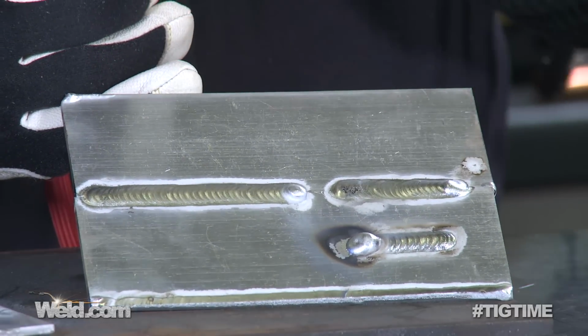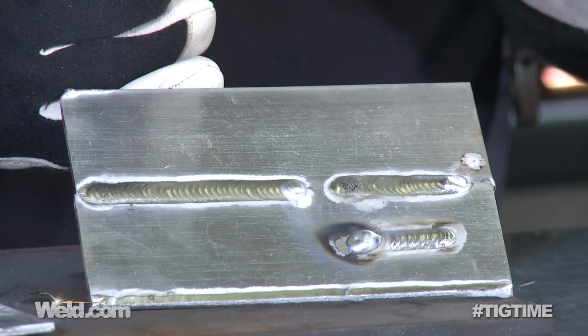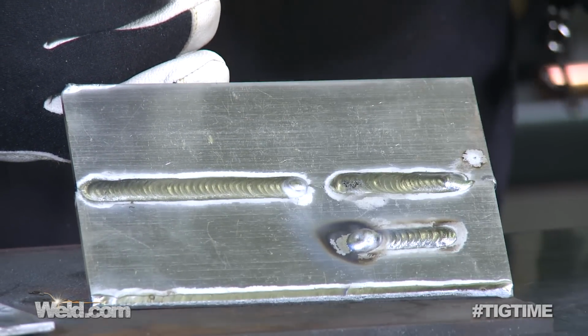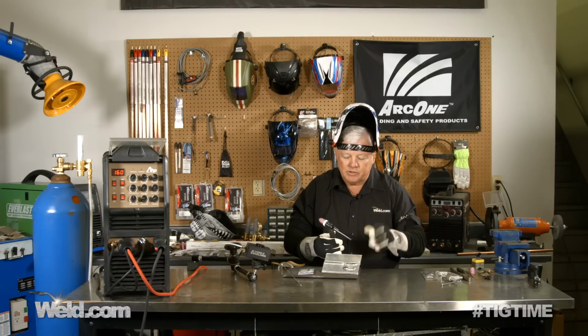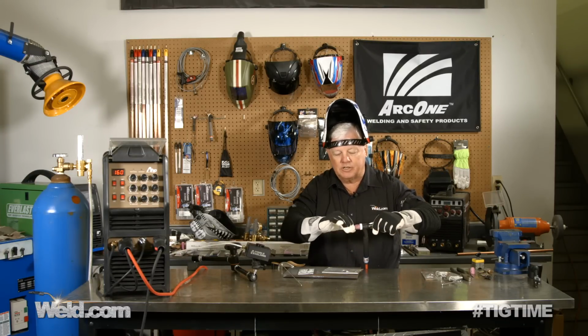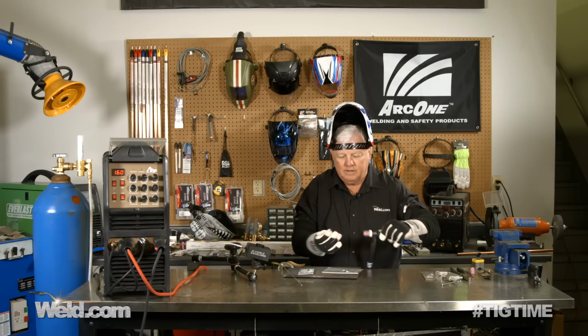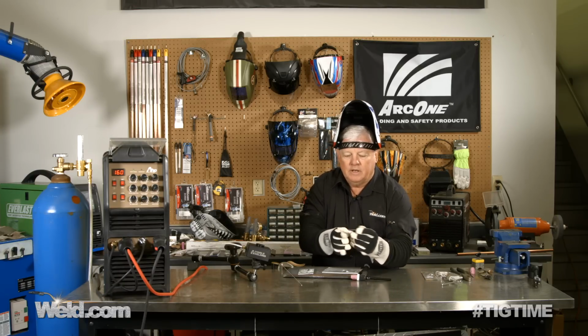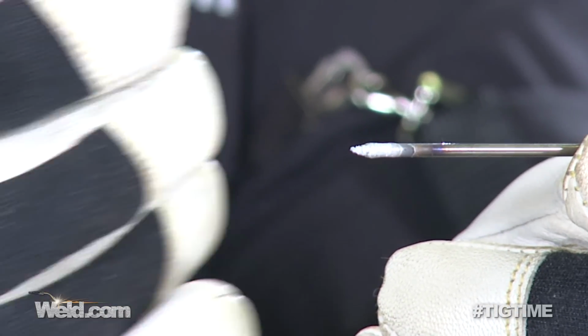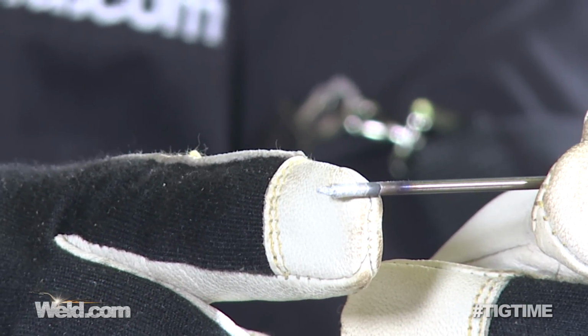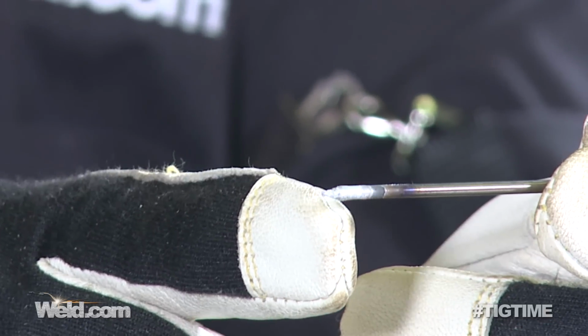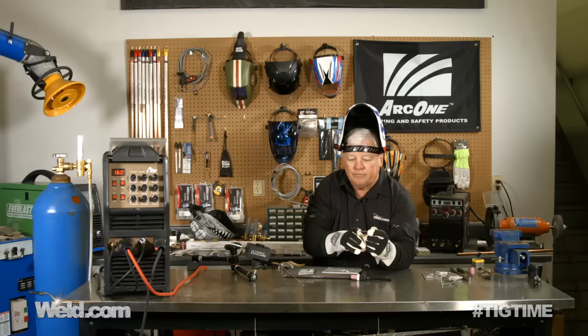Okay, the fact is, once the tungsten contaminates, the weld's going to be unstable. It's just going to have the uglies. So make sure that you actually take the tungsten out completely. And if you look real close, you see these crystals? That's actually aluminum. Aluminum has sucked up to the tungsten. I need to break off that tungsten because you can't grind it off very well. It camouflages too well. So I've got to break off about a fourth of an inch of my tungsten.